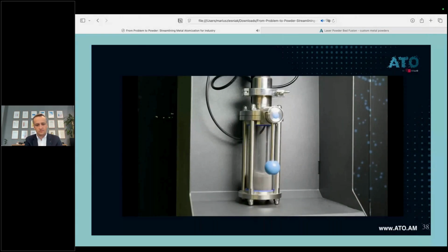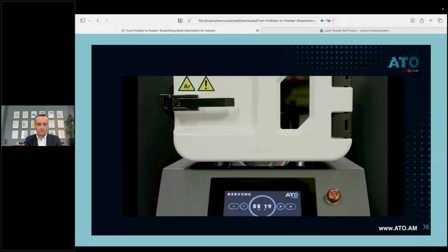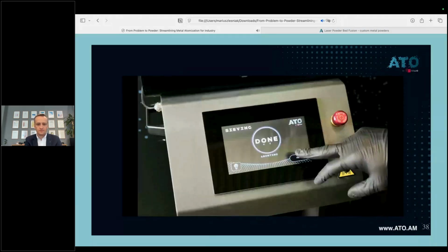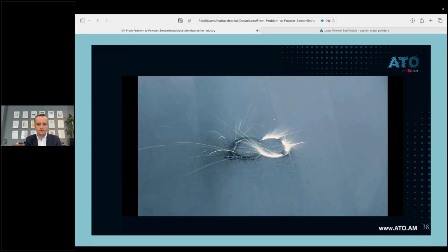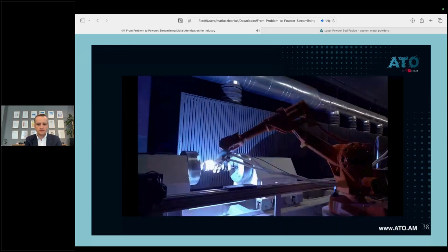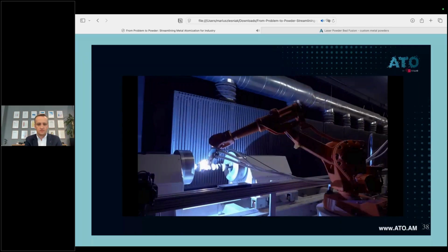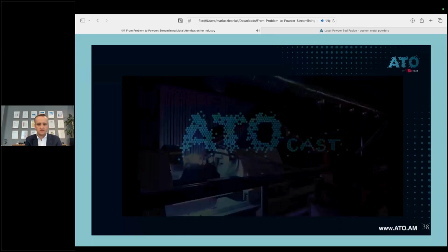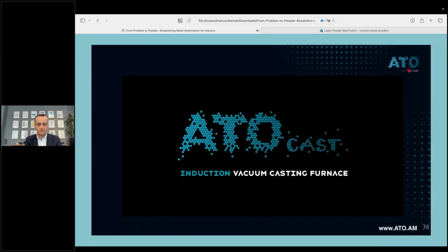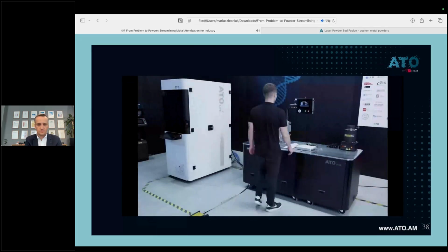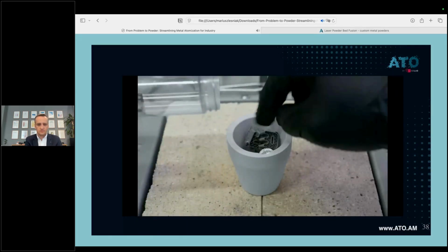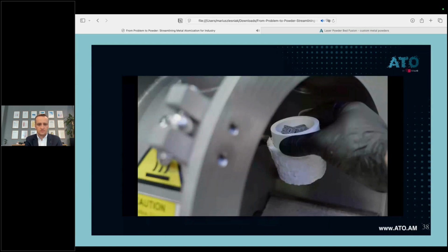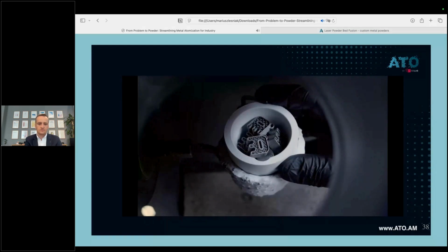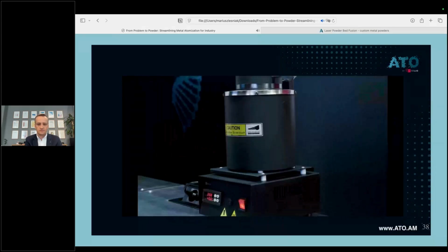ATO metal powders are ideal for use in additive manufacturing and advanced applications, with excellent flowability and narrow particle size distribution. Close the loop and recycle metal scraps from 3D printing with ATO Cast. It's a professional induction vacuum casting furnace with a compact all-in-one design. Fill the crucible with your metal or 3D printing scrap and mount it securely in the induction coil. By preheating the casting mold, you're reducing the risk of defects during casting.